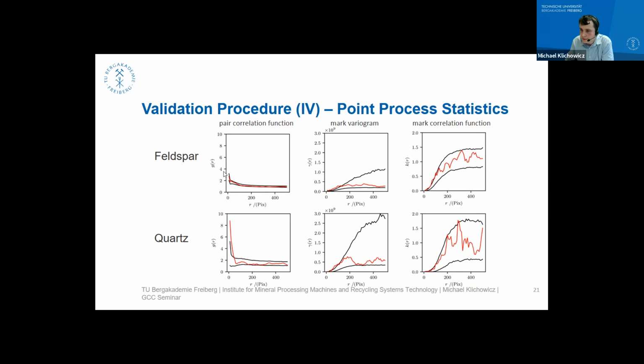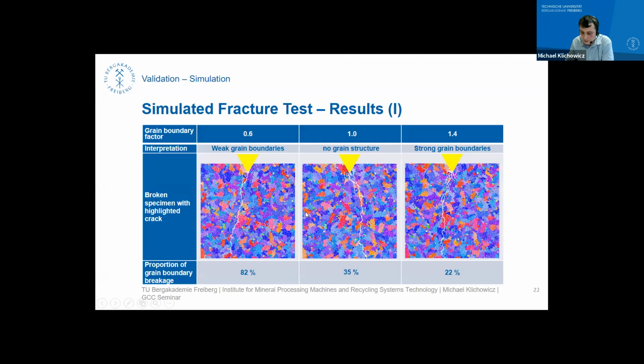Furthermore, we see that our measured real example is nearly always inside the simulations, which indicates that we have quite a good model for our granite here. Okay, so now we are at the point that with those measures we used, we can state that we have a realistic microstructure. And now I just want to give you a short outlook on how we can use this microstructure.